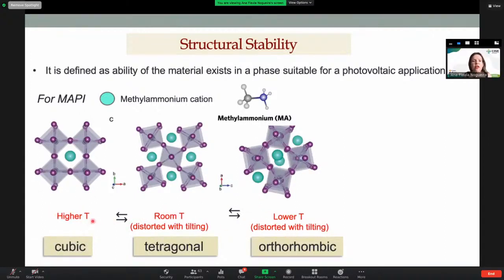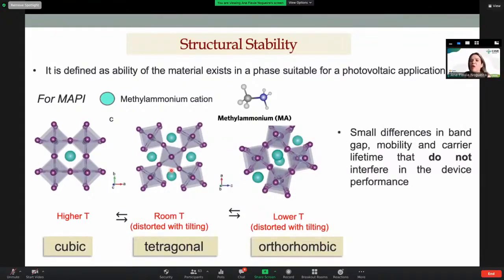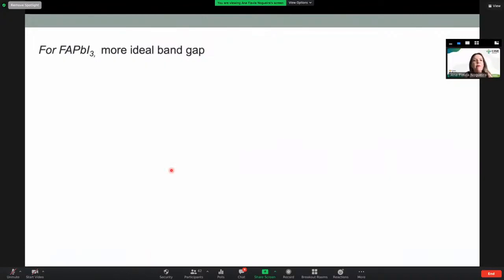So there were always people really concerned in the beginning whether these transitions could affect the device performance. Because of course, if you are changing the structure, you're changing the band gap, the mobility, the carrier lifetime. But it was also proved recently that it doesn't matter, because this small difference, from cubic to tetragonal to orthorhombic, does not interfere with the device performance. However, the same is not true for FAPI. FAPI is the perovskite with formamidinium instead of methylammonium.